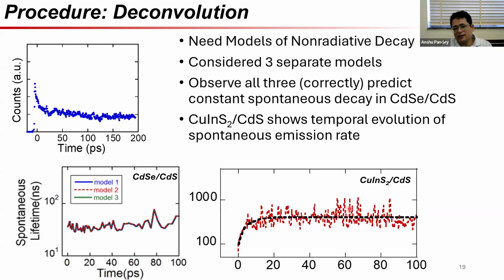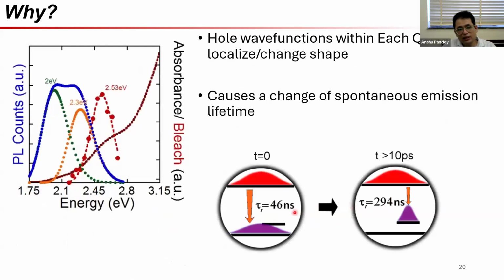So why exactly is this happening? As Professor Bagchi already anticipated, there is some kind of electron transfer going on. Very specifically, there is also a very subtle change in energetics, which is important, but it's so subtle and so instantaneous that one might miss it if we don't look at the spontaneous lifetimes very carefully. And the entire point here is that the valence band holes in this material, which PL is very blind to, are initially in a very delocalized state. It appears, at least, to be like that.